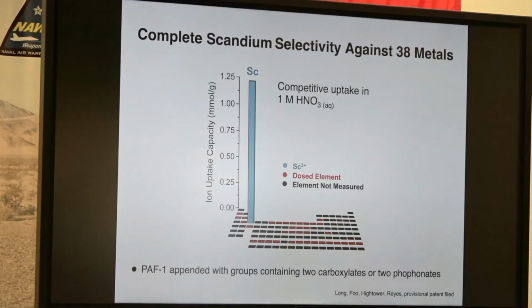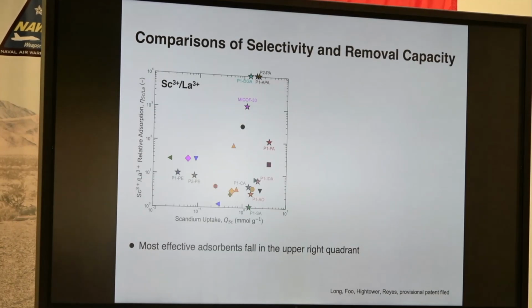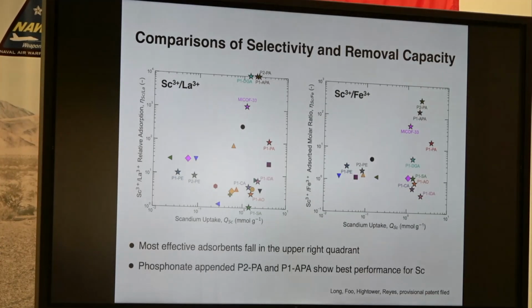And it turns out two of these materials are incredibly selective for scandium. So scandium is one of the rare earth metals, and it's the most charge dense one. So scandium 3+, you can see all the other metals here. This particular PAF, if you have a mixture, it just grabs scandium. And it's extremely selective for scandium over other lanthanides. So here, the vertical axis is selectivity over lanthanum 3+. Horizontal axis is scandium uptake. The best adsorbent will be at the top right quadrant. And the two polymers that I just showed you are at the very top in terms of selectivity. Also, selectivity over iron is important for scandium recovery. Again, those two polymers are at the top right.